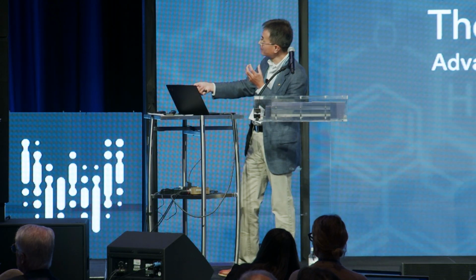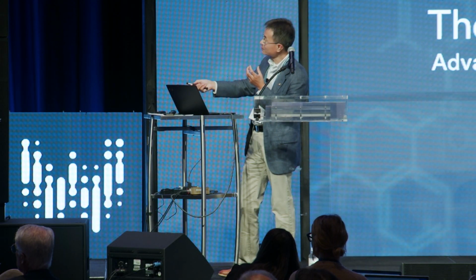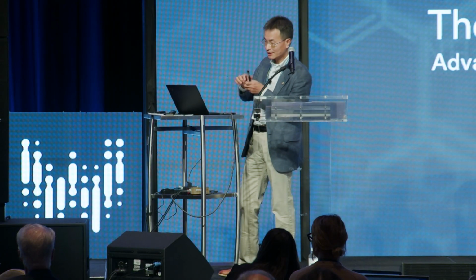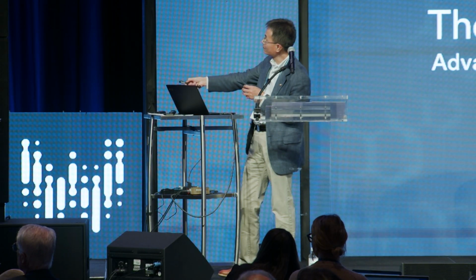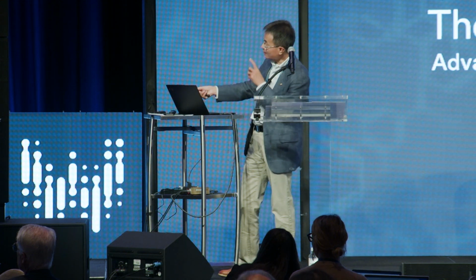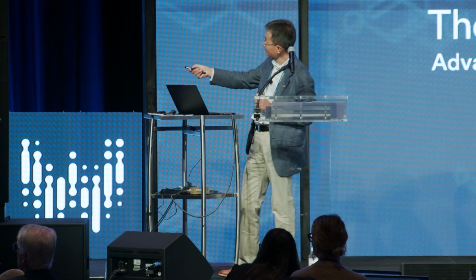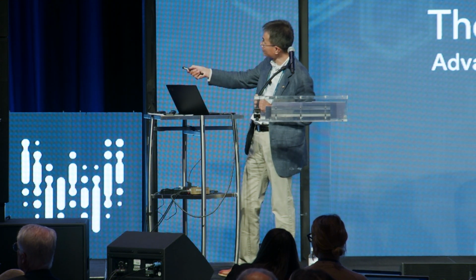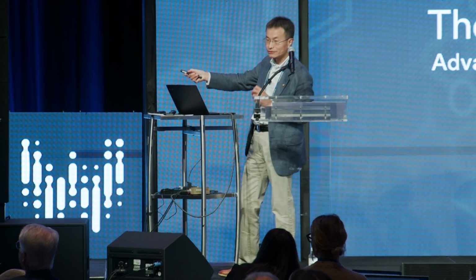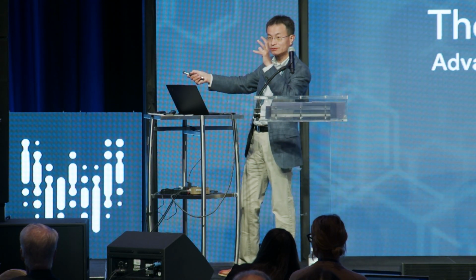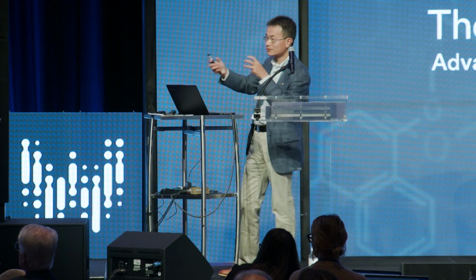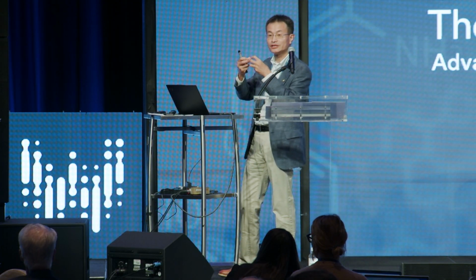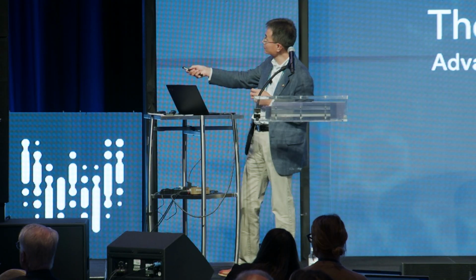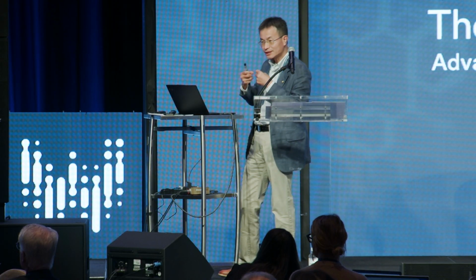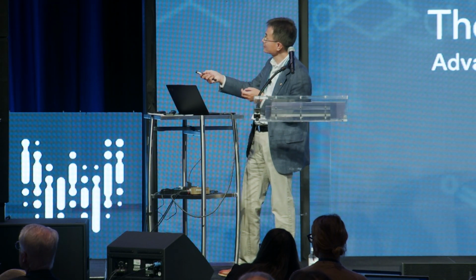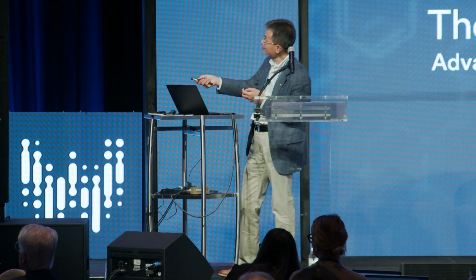But once you cross into this biphasic region, it's telling you that you are going to see two things. One is liquid, this is the liquid line. Another one is single crystal germanium. And that's exactly what we're seeing here. At high temperature, initially pure gold is solid. Once you start to alloy with germanium, it becomes a liquid puddle on the TEM grid. This is a gold-germanium liquid puddle. Then you keep adding vapor into the system. This is VLS.